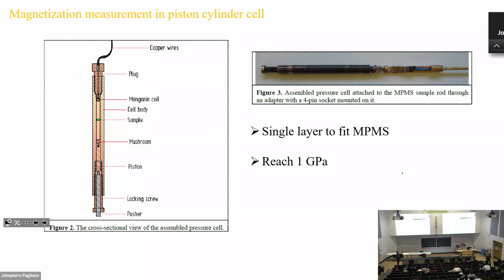So actually, in the original Bridgman setup, there is no pressure medium, and it's assumed that the pressure is uniform. The idea is that in the vicinity of the top layer, the sample might go into some very soft shape, and that will redistribute. So even though you apply pressure uniaxially, it redistributes inside the sample, and there's some force along this direction that applies pressure inside your sample. So the assumption is that even though you apply pressure like this, you still have a more or less uniform pressure. There is no way you can know how much.